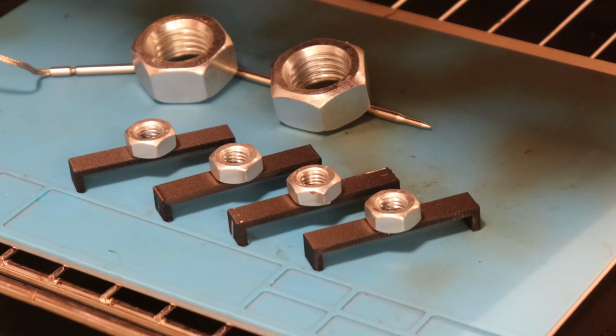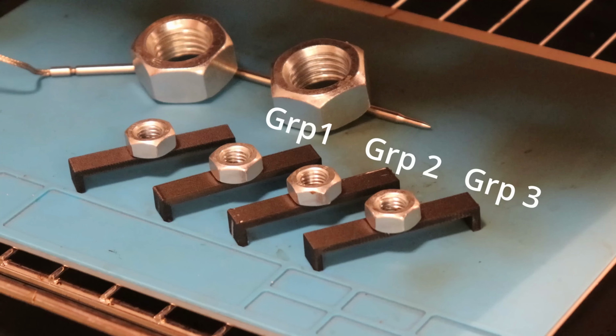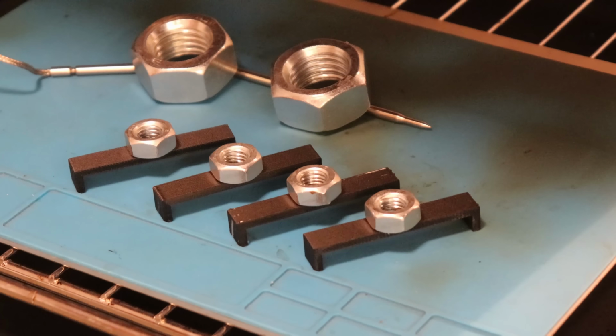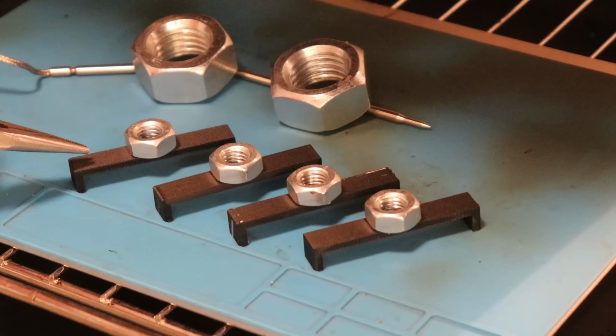Temperature test in the oven. These three are these nylon filaments, and I believe that they will not even start with deformation at 200 degrees Celsius, but I have to stop the experiment there, and I will see how hard they are. And this is some carbon fiber ASA, and I believe that I have to take this out much earlier. This is a sped up time-lapse video, and the first test objects started to deform earlier, and at 150 degrees Celsius I opened the oven and took out this ASA part.